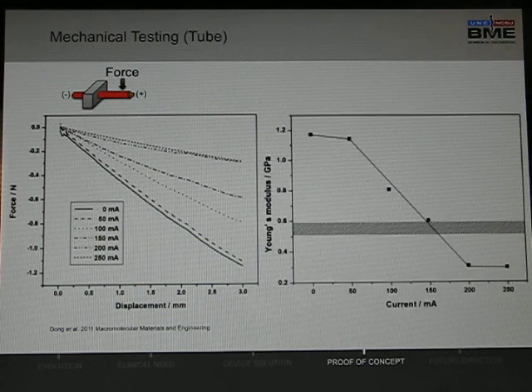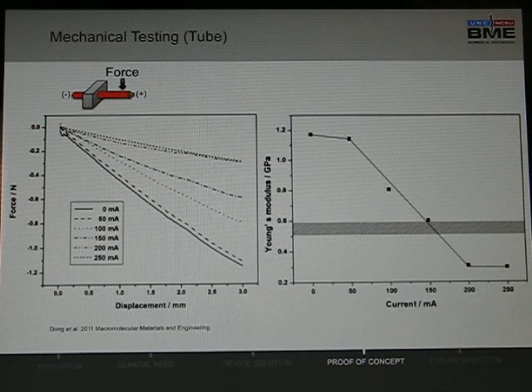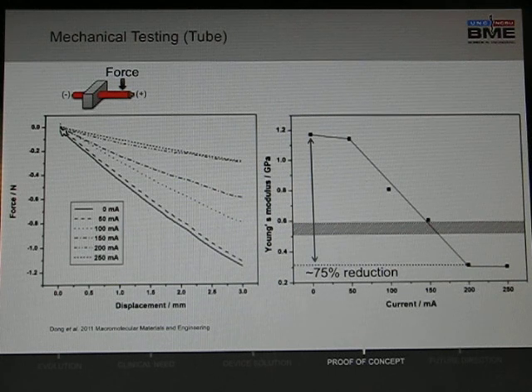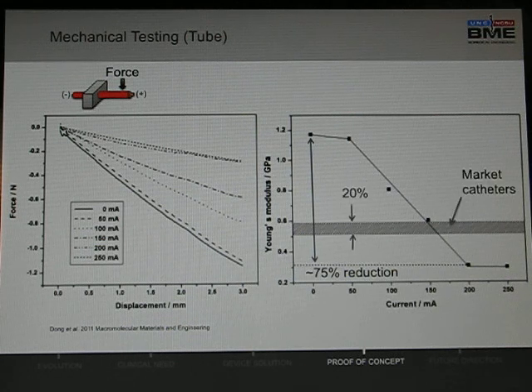If we extract out the slope of these lines, you get a modulus, or Young's modulus. We can plot this over the currents applied. We get a sigmoidal distribution. There is a reduction of approximately 75% from the inactive state to an active state of 200 milliamps. We have shaded out the stiffness range of a few market catheters we measured, and they span approximately 20%.